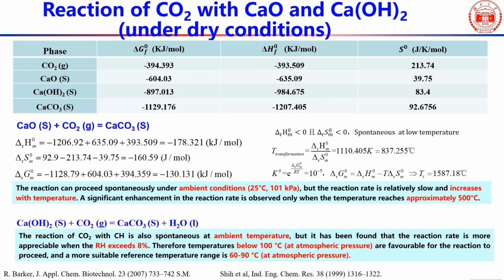Let's have a look first at how carbon dioxide can react with calcium oxide and calcium hydroxide. Thermodynamically, even under dry conditions, you can see the Gibbs energy for both the carbonation of calcium oxide and calcium hydroxide is very negative. So this means the reactions can happen very easily. But on the other hand, their reaction rate under dry conditions is extremely low.